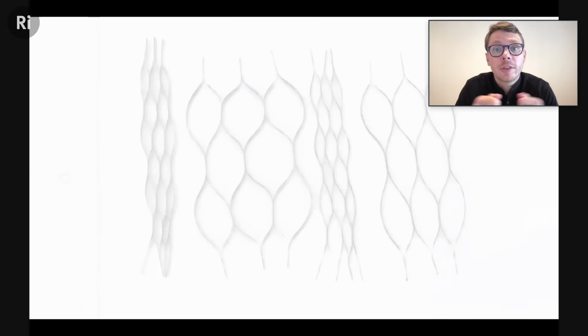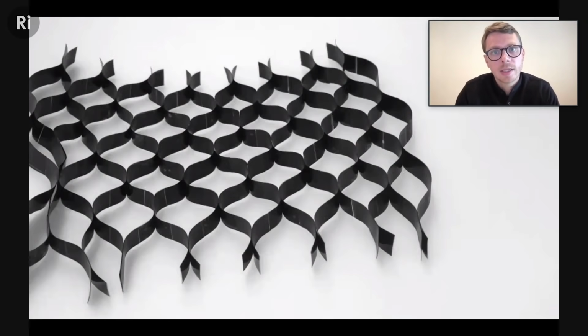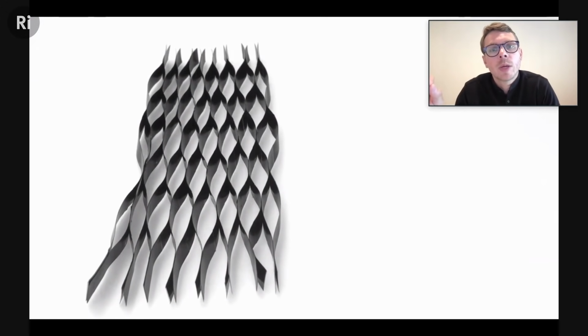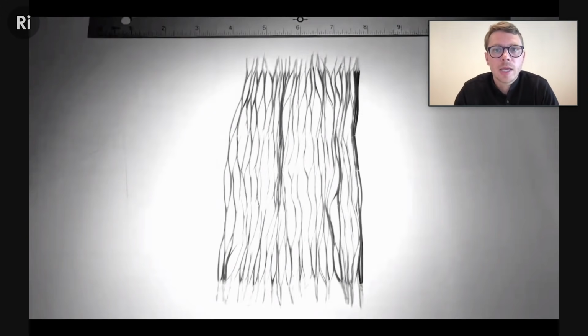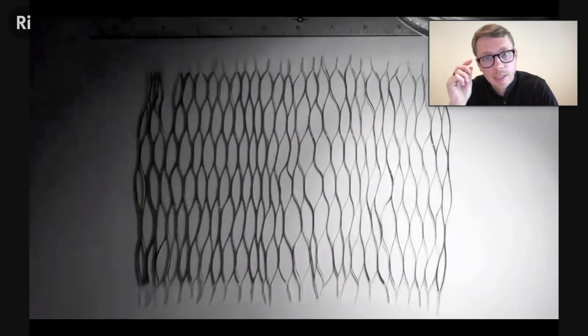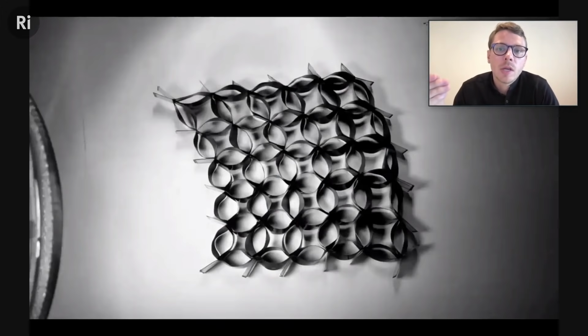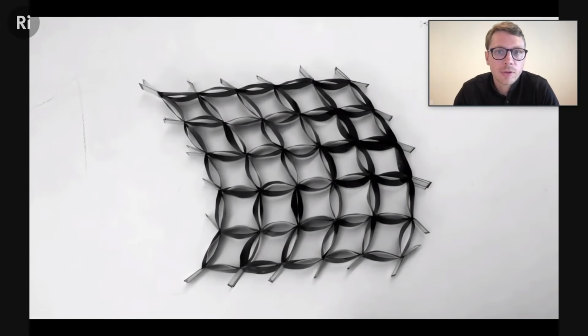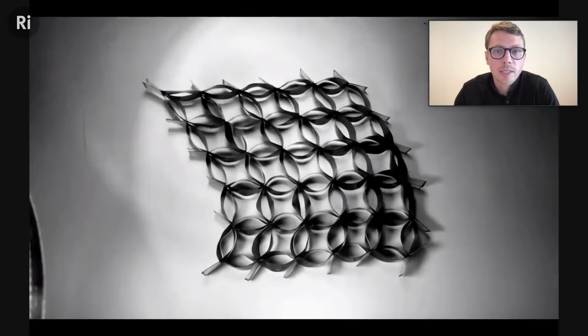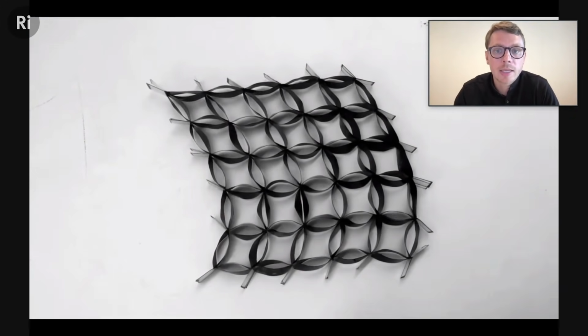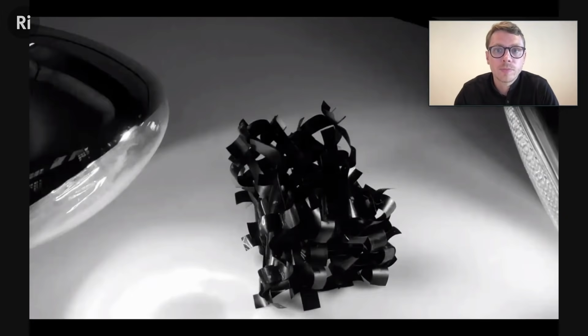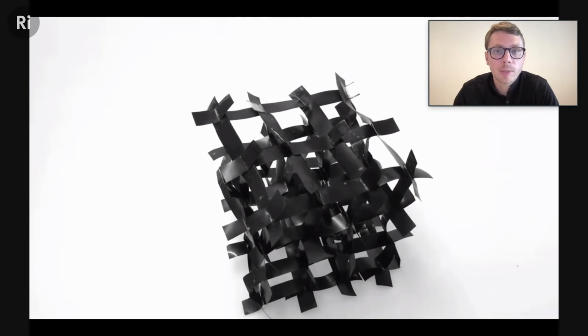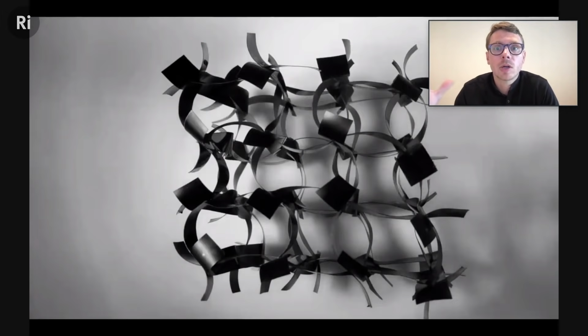looking at film. So thin films that we could slit into these strips. And when we recombine the strips, you can make essentially macro scale textiles. And these films are highly active with roughly 30 to 40 Celsius or direct sunlight. They can transform in seconds and they're totally reversible. And we can make two-dimensional and three-dimensional structures.